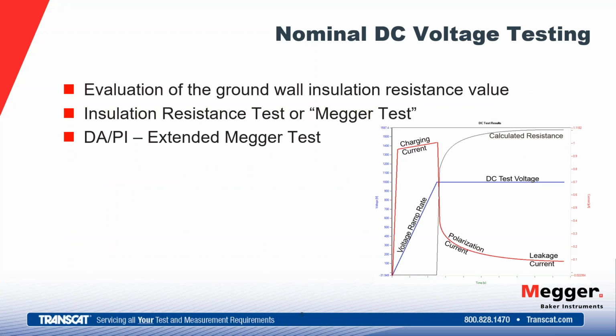The second test here we talked about is the nominal DC voltage test. Here we're looking at, again, the ground wall insulation. We're going to evaluate the ground wall insulation value, the insulation resistance to ground. So we're going to apply a voltage. We're going to measure current. As we measure current, there are lots of currents involved as soon as we start applying voltage to this system. You can see the graph there to the lower right. As we ramp our voltage up, mostly what we're measuring is going to be charging current. Then we're going to let our voltage be steady.